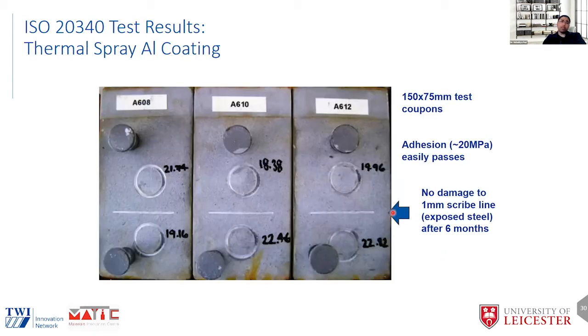However, when we looked at the thermally sprayed aluminium system, we can see in the scribe region there is no rust. We only saw some white products formed. I'm going to talk about the products in a bit more detail in the next slides. And the adhesion values, even after testing for 6 months, are 18 to 22 megapascal, which is very encouraging.